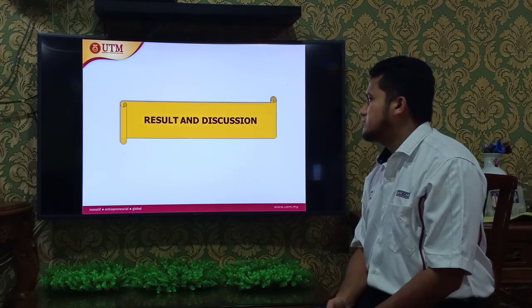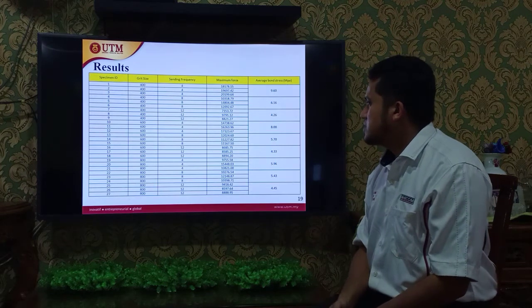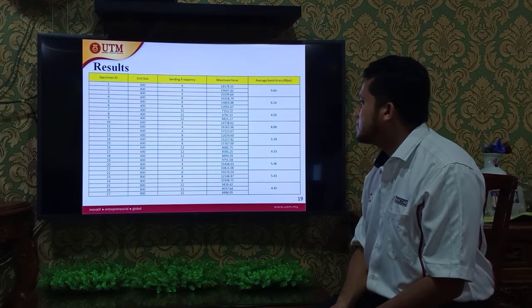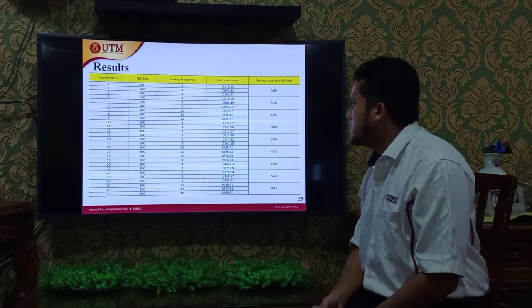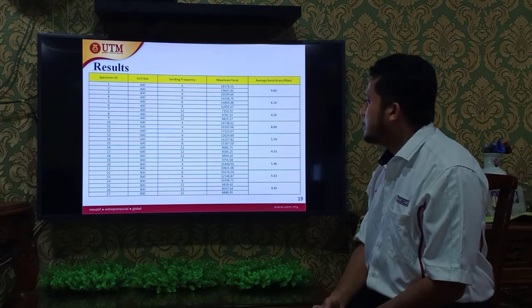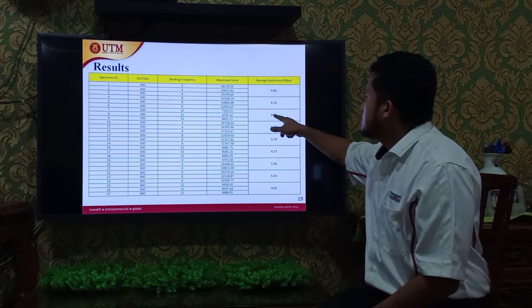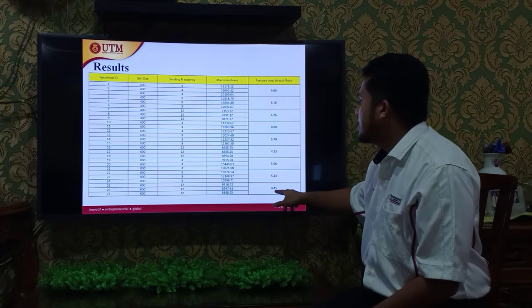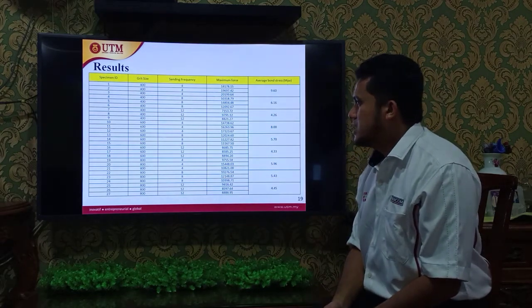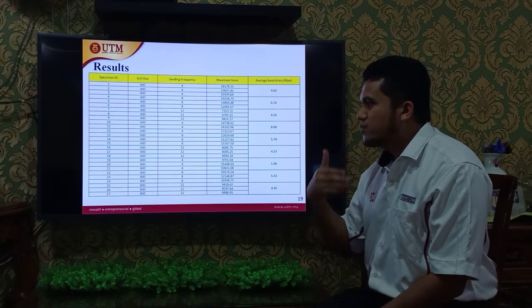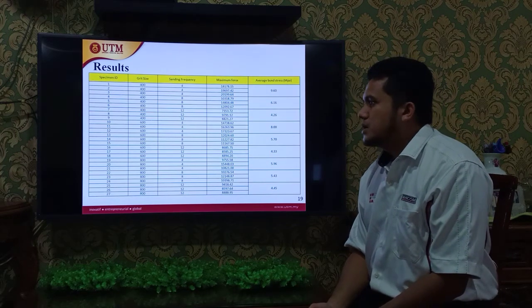Okay, we proceed to results and discussion. As the table shows, the highest average is for sanding frequency, preferred grit size 400 with 4 times sanding frequency: 9.60 megapascal average bond stress. While the lowest bond stress, as we can see from the table, is when we increase the sanding frequency to 12 times. The data show average bond stress equal to 4.26 for grit size 400, 4.33 for grit size 600, and 4.45 for grit size 800. In my opinion, if we increase the sanding frequency to 12 times, the average bond stress is slightly equal to 4.34 megapascal.